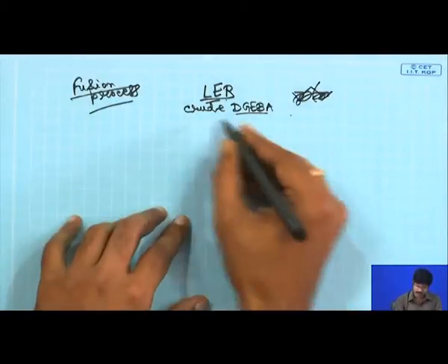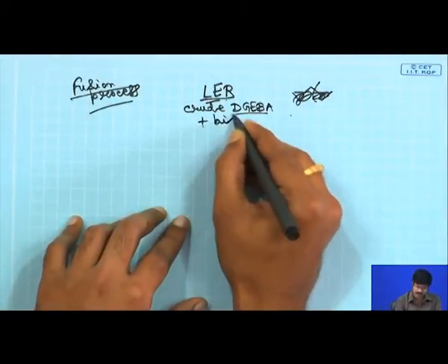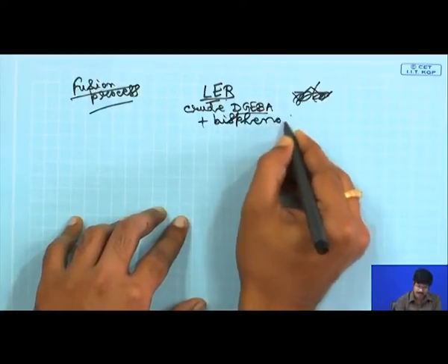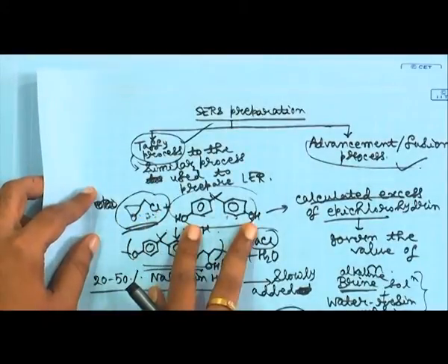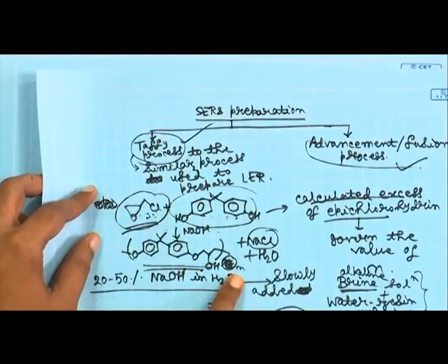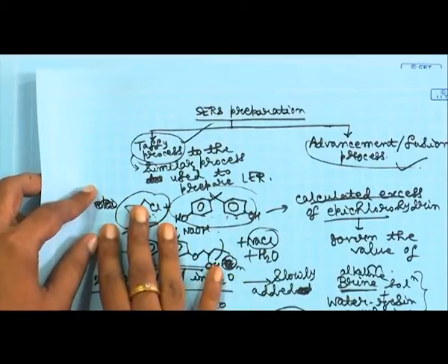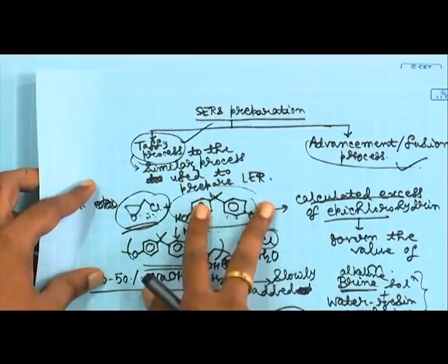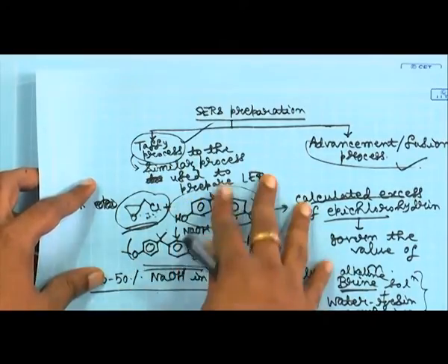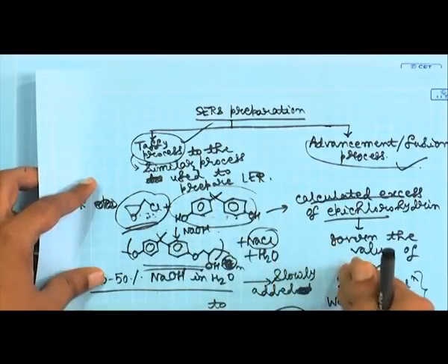You take that and you react that with bisphenol A again, because you know that when you are doing this epoxide preparation, it depends on the ratio. If this ratio is lower, then the N value is higher, but in this case you already take a high ratio, so the N value is lower, and then you add a further amount of bisphenol A after. So, the process is the same, it is a two stage process now.